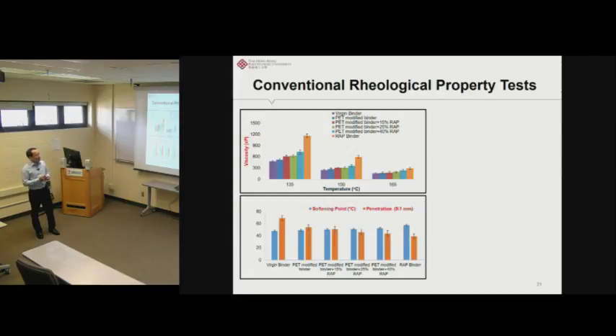And following the anti-stripping test, we also did the conventional viscosity, softening point, and penetration tests. So here, the plot on top is for the viscosity. The first column represents the virgin binder, always the virgin binder, at different temperatures. And the second column, the blue column, represents the PET modified binder. And the following are those PET modified binders with increasing amounts of RAP binder.